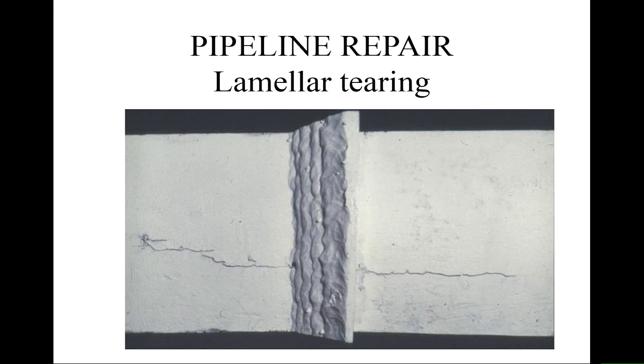This is a lamellar tearing example here where we've got the through thickness case. We've got a weld that's been done, so we've got these welds being done vertically in this particular case here, and the tearing is towards the middle of the thickness of the system. So what that's telling you basically is you don't necessarily see any evidence for the lamellar tearing on the surface. You need this non-destructive testing.